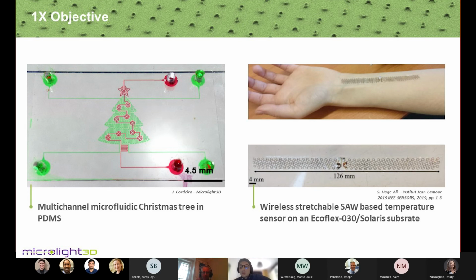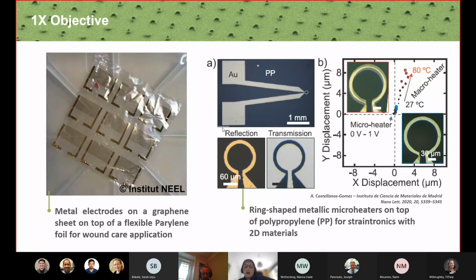wireless stretchable surface acoustic wave-based temperature sensor that has been fabricated on a silicon substrate and then transferred onto this EcoFlex/Solaris substrate, which is, as you can see, a stretchable and transparent substrate. Here, the pattern has not been fabricated directly on the stretchable substrate, but transferred using a stamping method from the silicon substrate onto the stretchable substrate. However, it's possible to work directly on transparent and non-flat surfaces.